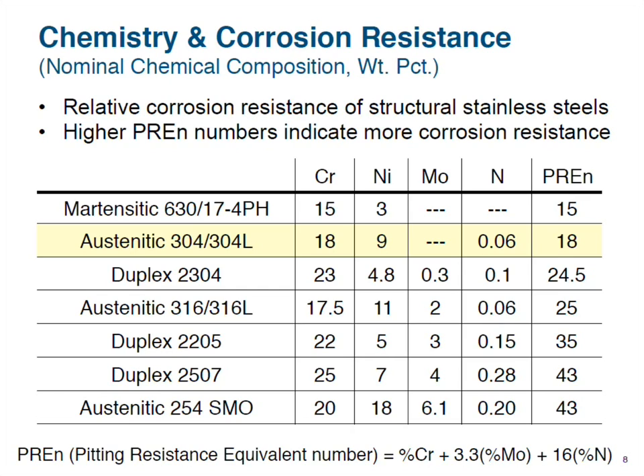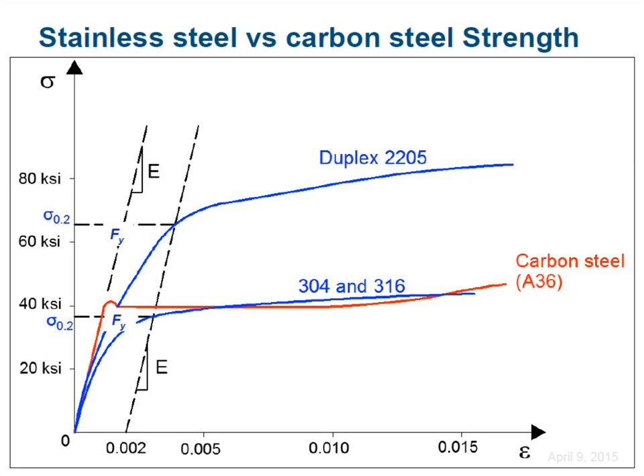You can see that 304 is at 18. 316, you're probably familiar with, is at 25. As you go all the way up to those that are in the 40s, those are stainless steels that can be immersed in seawater and not corrode. So there is a wide range.